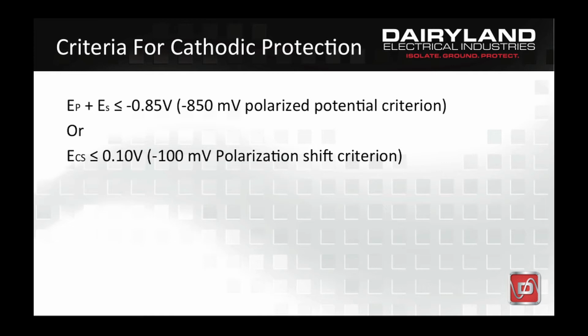However, to determine if the minus 100 millivolt shift criterion is met, it is necessary to conduct two surveys, an off-potential survey and a depolarized survey. To do this, the rectifier is left off for a period of time, sometimes weeks, to allow the pipeline to depolarize completely, after which a close interval survey of the pipeline potentials is taken. The corrosion potentials on the depolarized pipe are then compared with the polarized potentials to determine if a minus 100 millivolt shift is obtained at all points along the pipeline.